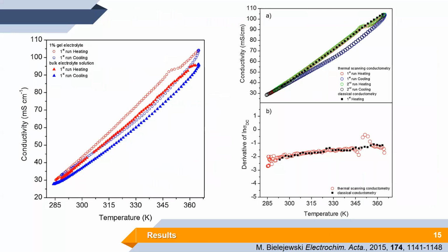And this is an example of the data we get from the thermal scanning conductometry. On the left-hand side figure, you can see the conductivity of an electrolyte solution consisting of tetramethyl ammonium bromide salt dissolved in water. The solid symbols, the triangles, are for a liquid electrolyte, and the open circles are for the ionogel. So this is actually the reason why we were so interested in this project. You can see that this is something against our intuition. In the gel phase, when we go from a liquid, a very mobile system, to a solid-like system, where the bulk flow is stopped and the motion is more restricted, we actually observe that the conductivity of such a system is higher than in the liquid phase. So this is something we were not expecting to find.